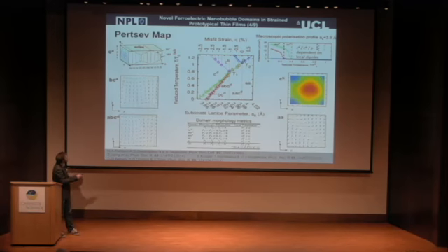If you increase the strain and temperature back towards the freestanding limit, you get this transition path where you go into these BCD domains, which have the same cross-sectional profile as the CD domains, but have this in-plane component. And then you get this ABC domain pattern here, which has this kind of continuous dipole wave along x, as well as an in-plane component, while maintaining these closure domain-like patterns.